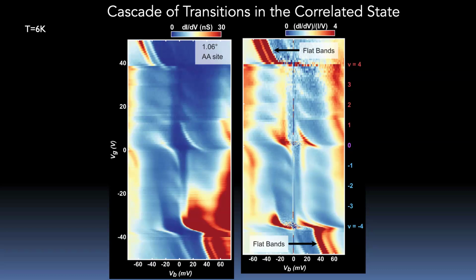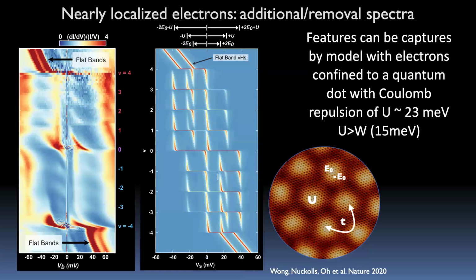So right away, we can just look at this raw data. This is something we could never do in any other correlated system: tune it between the non-interacting picture and an interacting picture by just changing the gate voltage. Fill the bands, partially fill the bands, see what happens. We were very excited about this at the very beginning because it showed us that we really can see effective strong correlation in this process. So now you start to ask, what are these features we see?